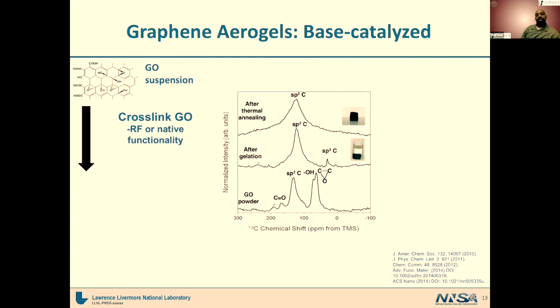Graphene oxide is basically what you get if you take graphene, a planar sheet of carbon with a hexagonal structure, and functionalize it with various oxygen-containing groups, such as carboxylic acids. Many of them are shown here in the GO powder from this NMR spectrum. You have carbonyl groups, hydroxyl groups, and some epoxides, and this is what makes the material easy to get into things like water, because otherwise graphene would not want to go into water. But it also allows us to cross-link our GO to form it into this three-dimensional network.